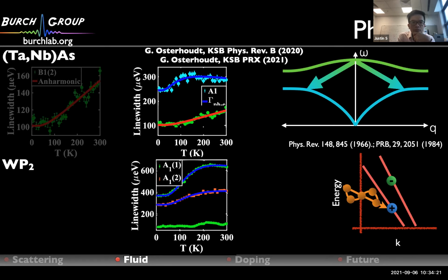And indeed, what's going on is, I think, consistent with your intuition, which is that depending on the Fermi level relative to this transition, that governs entirely the temperature dependence you see here, right? So essentially what's happening is when you start heating up, you're opening up more phase space for scattering, right? So for example, imagine this transition was happening above the Fermi level, right? So you start thermally populating up here, but then at some point you keep thermally populating and now you essentially have Fermi functions covering both of the two states. And you basically hit a wall. You can't scatter anymore because Pauli blocking essentially limits you. I see. Right, so that's basically why you see this plateau in the temperature dependence.